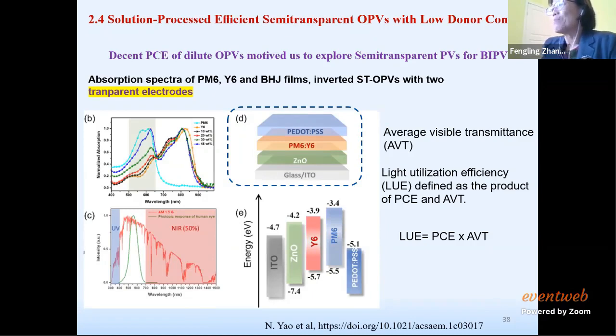Encouraged by this part of the work, we also found an application of the low donor device. Because you see, the acceptor is a low band gap material that absorbs the long wavelength photons. So if we decrease the donor content, then we can decrease absorption in the visible part. So then we can make a device even transparent, but it can still absorb enough photons to generate current. So here we use the same combination, still PM6 and Y6, but the work differs from the previous one. We just need the transparent electrode to make the device transparent. So the key issue here is finding a good combination for the transparent electrode.